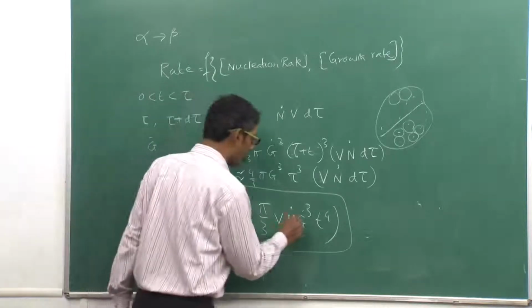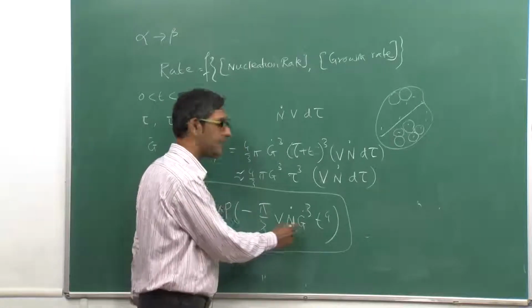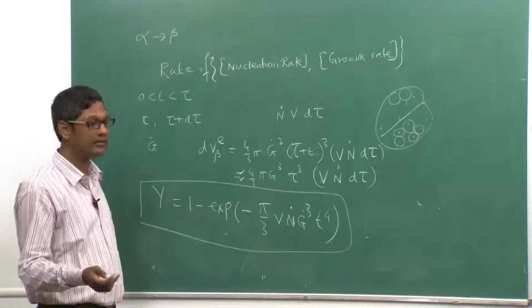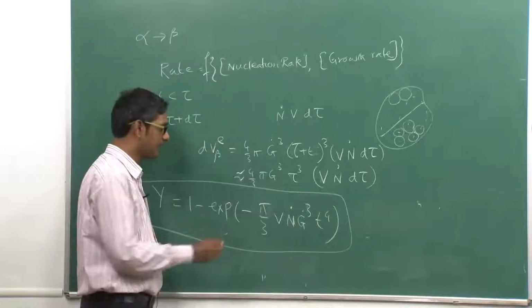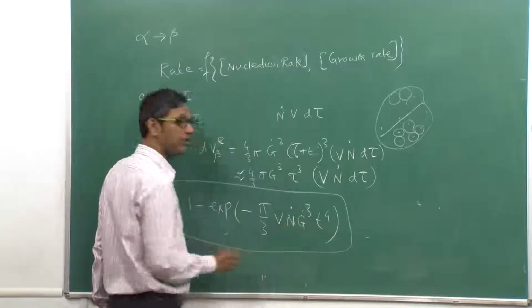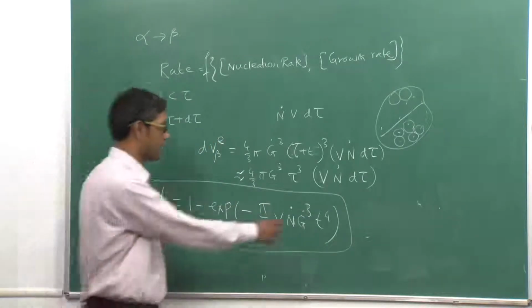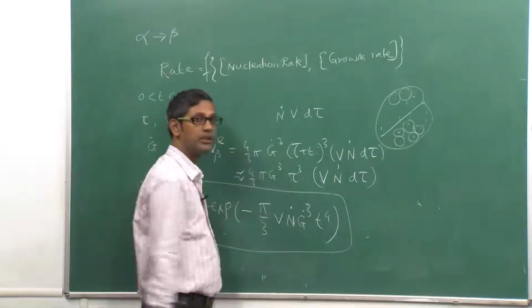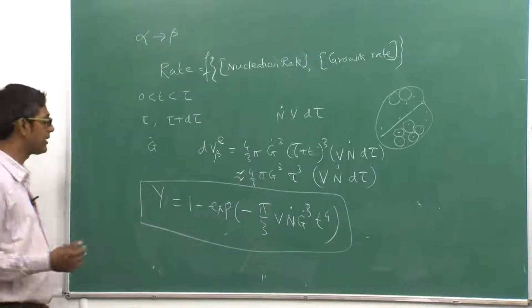In a pearlitic growth, diffusion controlled growth, G has a different kind of expression than in martensitic growth or in the case of recrystallization grain growth. So depending on the type of process, these factors G dot and N dot will change. And remember, the exponent on the time can change also, because in some processes it is a very strong function of time.